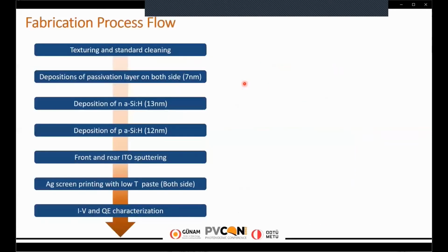Here, this is the fabrication process flow of a standard silicon heterojunction solar cell. The first step is the texturing and cleaning of the silicon wafers. Then, a thin intrinsic amorphous silicon layer is deposited on both sides of the silicon wafer. An n-type amorphous silicon layer is deposited on the rear side of the silicon wafer. On the front side, the emitter was formed by a p-type amorphous silicon layer. Then ITO was sputtered on both sides of the silicon wafer. The last step is the metallization. For the metallization, we have used low temperature silver paste.